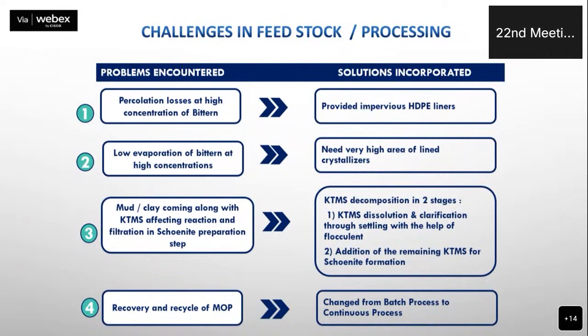So while working on the sulfate of potash, we encountered a number of challenges which are given here. So there are some problems encountered, and then what we did to come out of this problem. First one was percolation losses at high concentration of bittern. So when we concentrate bittern from 29 Baumé to say 36, 38 Baumé, percolation losses become significant, and evaporation decreases at high concentration. So what we did, we provided impervious HDP liners in the salt works so that we can reduce the percolation losses. And due to low evaporation, we kept this bittern in large area so that evaporation can take place.